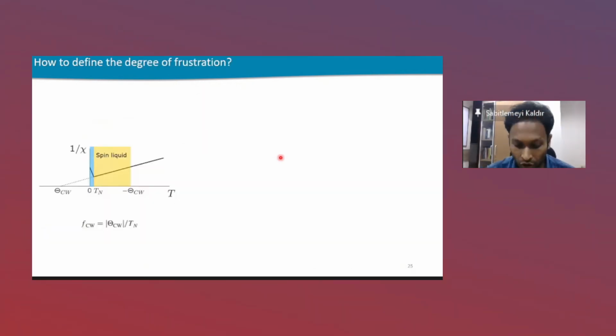Okay, so before going to this particular system, let me tell you one more thing: in a normal insulating system where you do not have any Kondo or RKKY type of interactions, the degree of frustration is defined by this parameter, as you can see. It is nothing but the ratio of the Curie-Weiss theta over the ordering temperature.